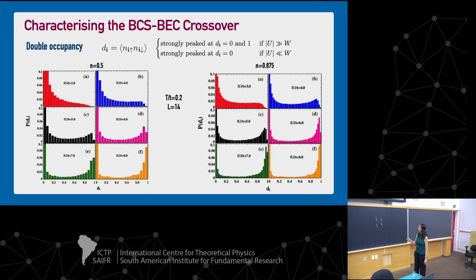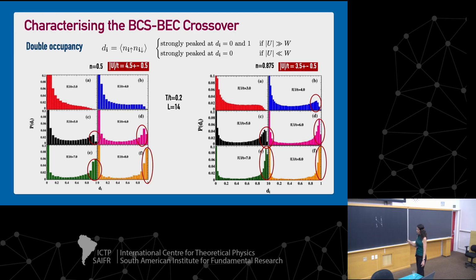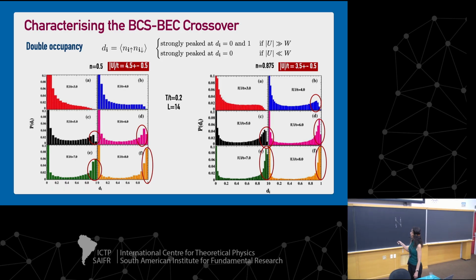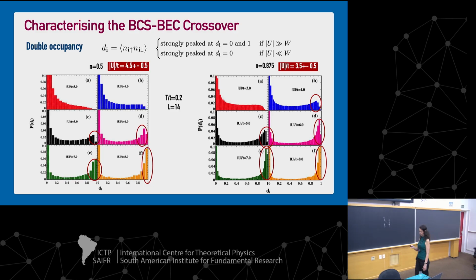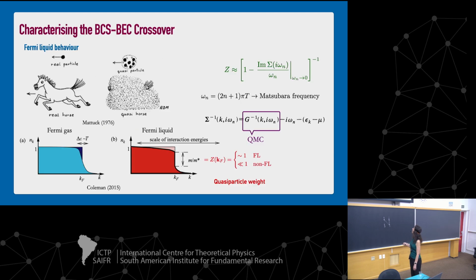And so here is what happens at a quarter filling density. And here we are increasing U, and we are looking at the statistics of the formation of pairs. And here at 0.875, we are also doing the same. And we see here that as we increase U, we start to have pair formation at some given value of U, here around 4.5, and here around 3.5, we start to have a lot of pairs forming at higher temperatures.